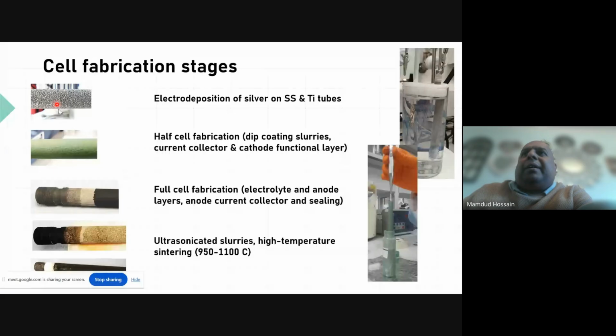So we have our tube, and we use 2 different tubes, one is stainless steel, one is titanium. These are all porous. This is our base structure that doesn't take part in the electrochemistry. It's just a support. On top of that, we need to put silver, because that is a current collector. Then we put a dip coating of slurry, the cathode functional layer. We build up one layer after another layer and after another layer on top of each other.